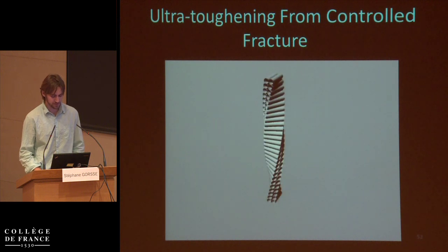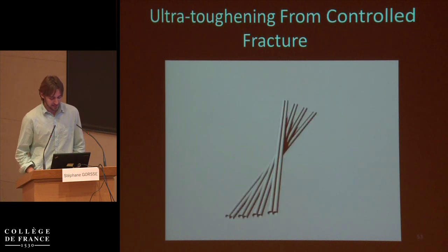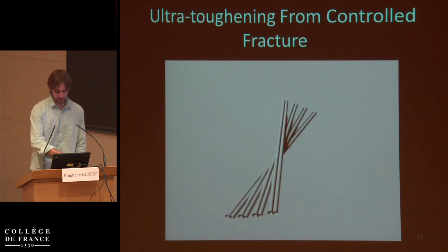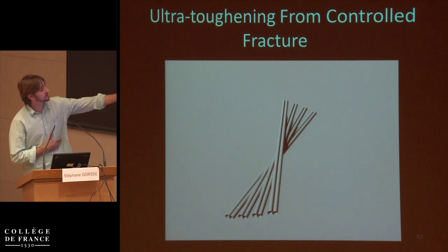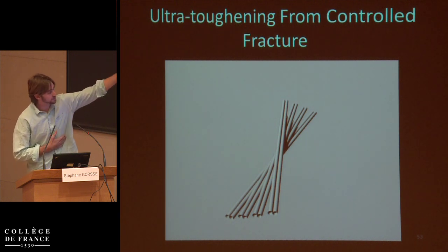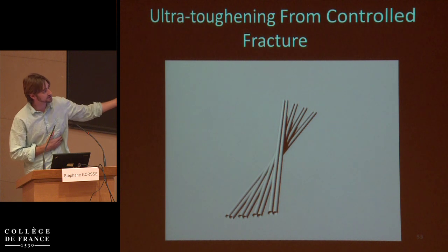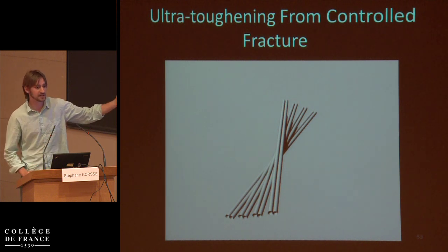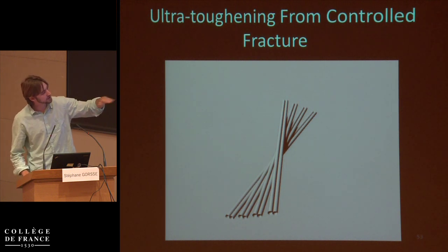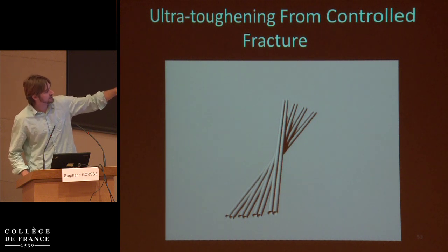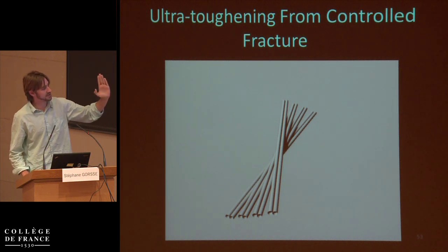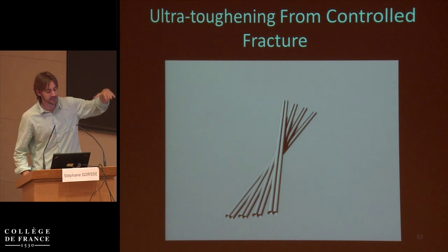But then the opposite of this would be, let's consider now a fracture that's growing radially, but not longitudinally. And so now what you see happens is that in order to travel between these two fibers, as you increase your radial distance, then it has to traverse a larger distance this way around the circumference. And what that does is it actually, the further you get out, the less angle you have.